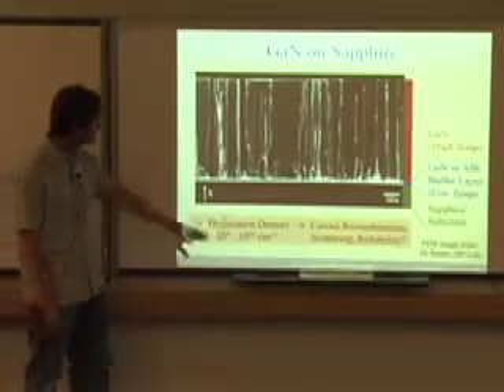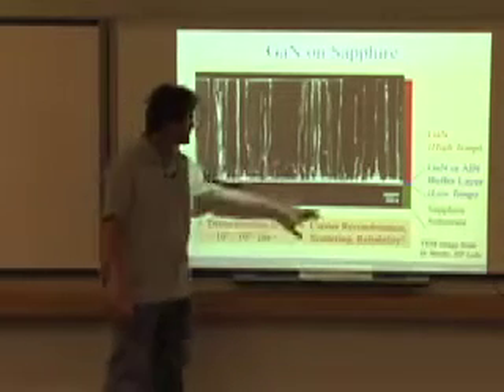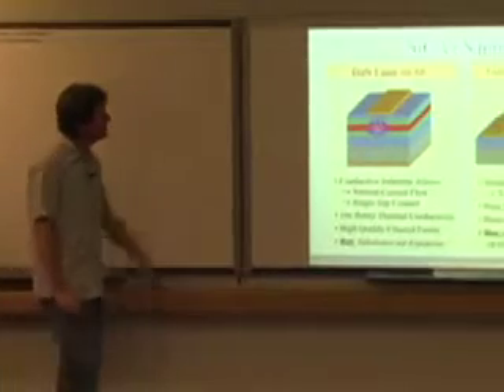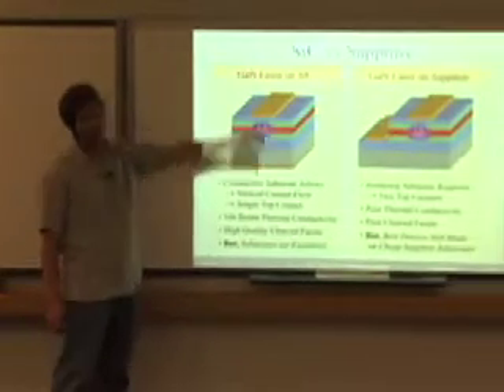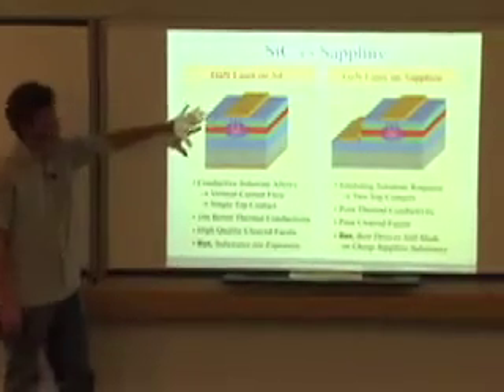But even when you do this, you still have very high dislocation densities, in the range of 10 to the 9, 10 to the 10th per centimeter squared. So you worry about carrier recombination, you worry about scattering, optical scattering, you worry about reliability. So clearly it's not ideal.